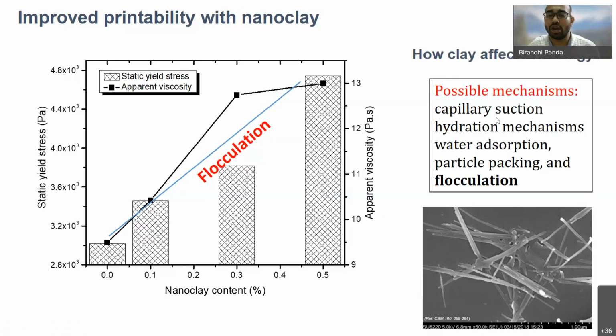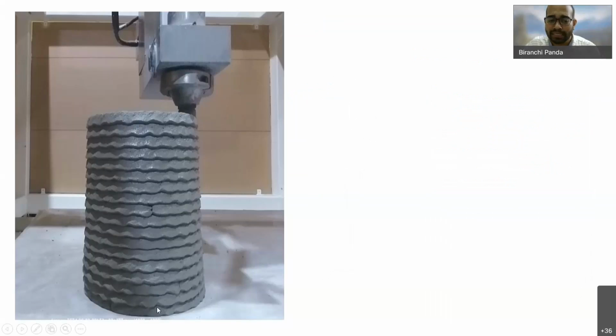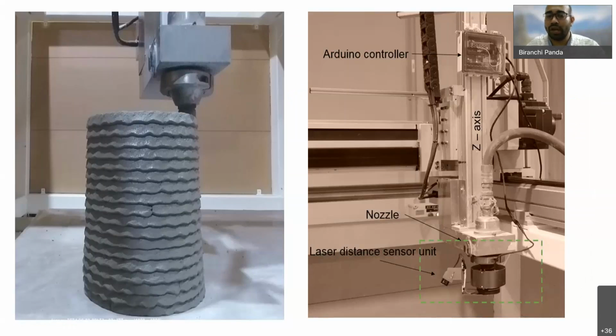So how does clay affect the rheology? There are several concepts that have been demonstrated in the literature, but especially in the case of printing concrete, we found the flocculation of the clay is very important, and it improves the yield stress to a significant value, so that I can now put more layers without any deformation. And as you can see, more layers have been added now without any deformation. So it is the clay that increases the flocculation, and as a result we can deposit more layers without any structural collapse. Sometimes, since these materials are very fresh, deformation happens.